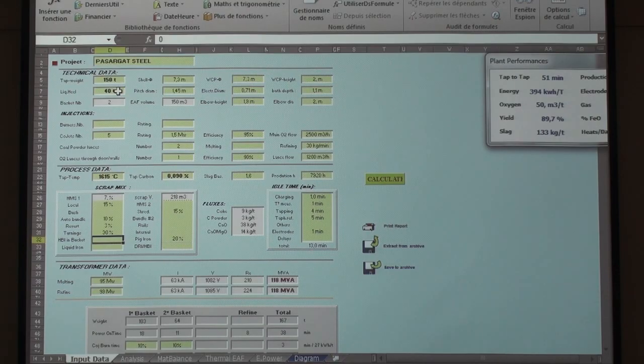But I've seen that increasing the hot heel also makes another disadvantage, because you need to maintain the bottom from time to time, once a day. Then you have to drain the furnace completely, and then you have to rebuild the hot heel again. So it destroys a little bit the smoothness of the melt shop, or you have to have more management. You need to cut down the scrap on the previous heat, and it even takes 2 heats to decrease the hot heel. It starts to be a nightmare. Even for a furnace having a low hot heel, I've seen sometimes they need 2 ladles to empty the furnace. They were expecting to have 10 tons and they had 40 tons, 50 tons.